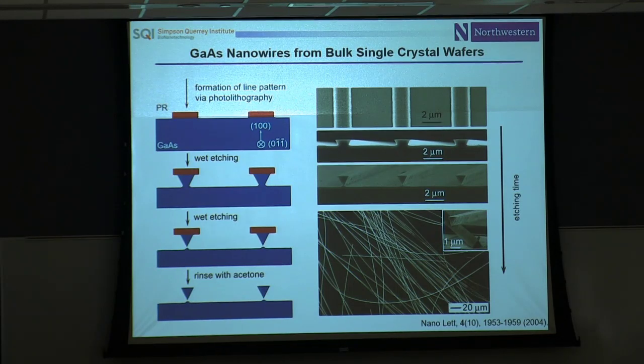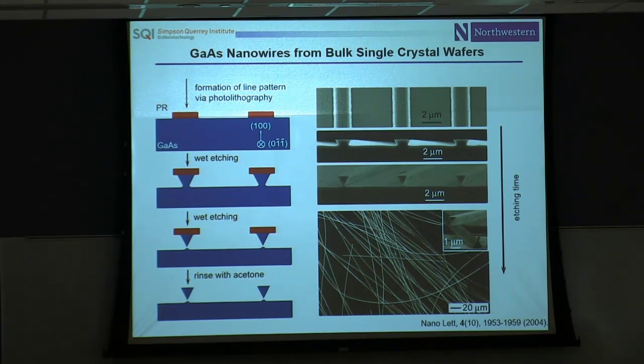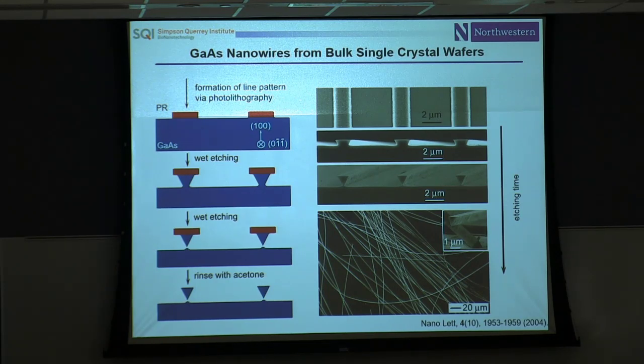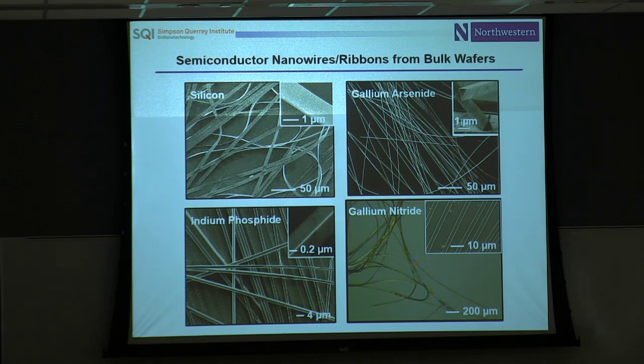There are other kinds of approaches you can apply to compound semiconductors, not just silicon. There are anisotropic etching tricks you can use with gallium arsenide to pinch off the near-surface region—in this case, triangular cross-section gallium arsenide wires—with bending mechanics defined by submicron characteristic dimensions. Similar ideas apply to indium phosphide and gallium nitride. You can create a whole portfolio of semiconductor nanomaterials starting with wafer-based forms, without reinventing growth techniques.